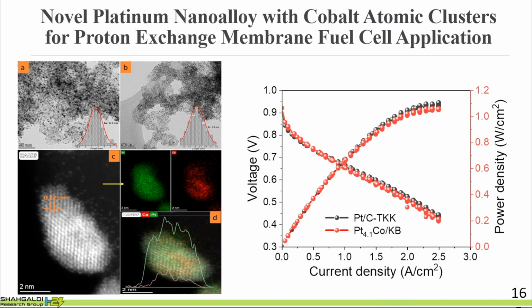So this is another work that is under publication, that we recently published. We tried to build an alloy of platinum and cobalt. We did a lot of synthesis, and this is the polarization curve that we recently got. It shows that with almost half of the amount of platinum inside the stack, we got almost the same polarization curve and the same power density.